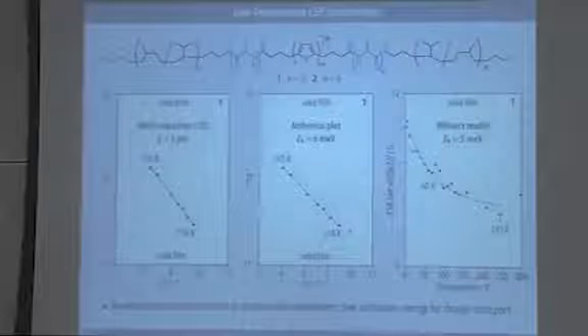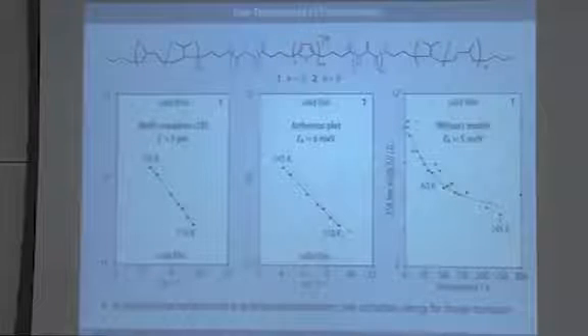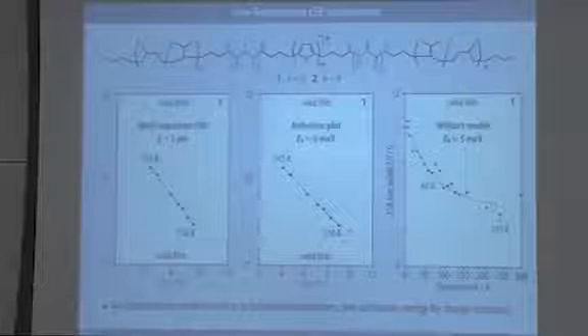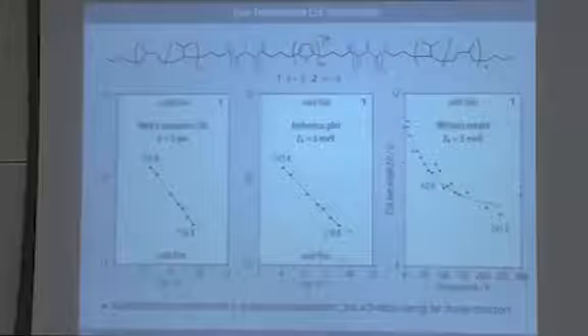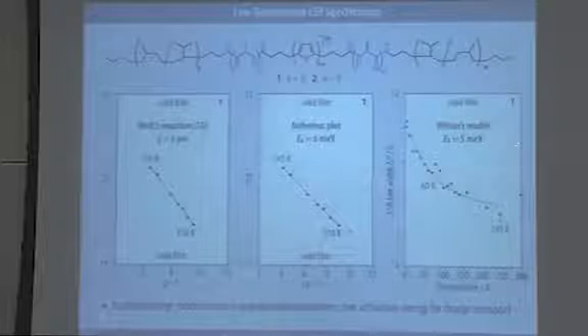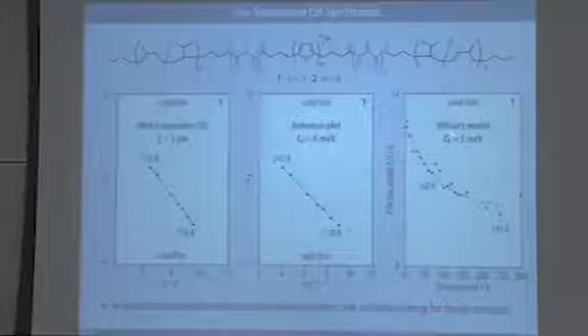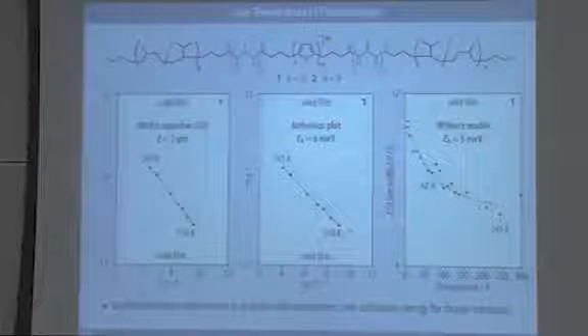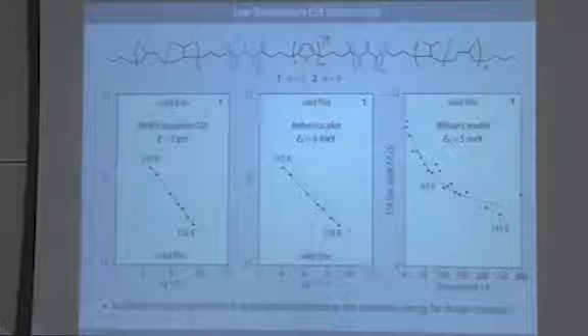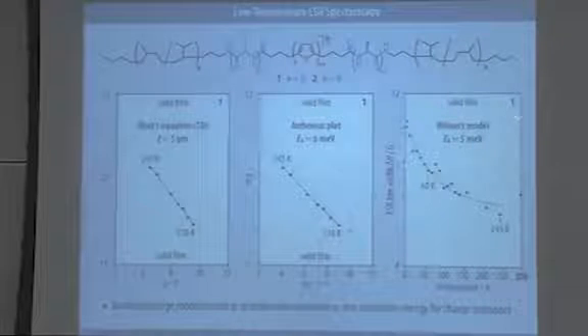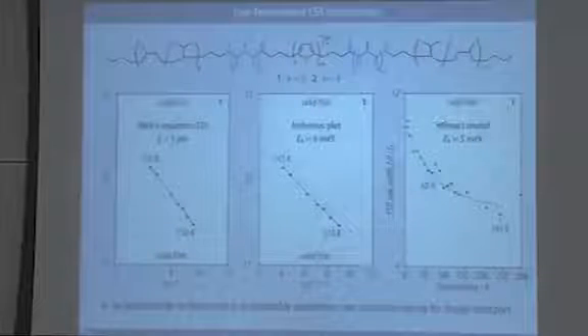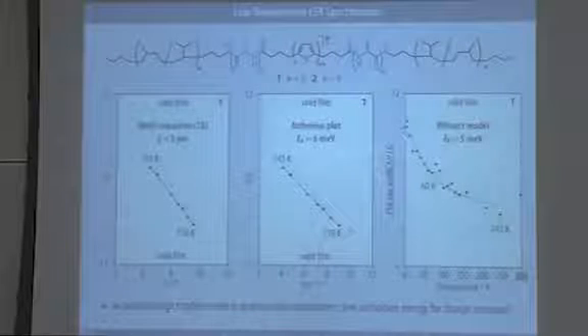And a similar borderline case has recently been reported for carbon nanotube networks, where people have fitted similar ESR data as we did, using Anderson's model for motional narrowing combined with a hopping wave function, which was then termed Wilson's model. And again, if we fit, we actually get a nice fit.